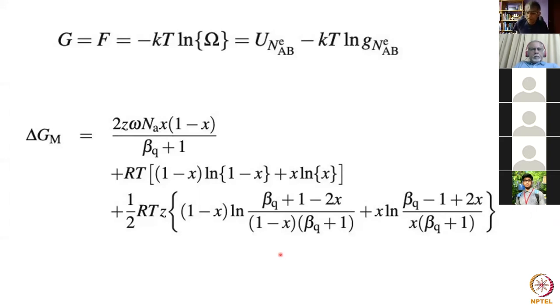The other point is that a lot of the equilibrium thermodynamic data will be derived at high temperatures, because you cannot really achieve equilibrium if you go to sufficiently low temperatures. That means that if you try to extrapolate those functions, you might get some strange results using thermodynamic databases alone. So this method also enables you to extrapolate to low temperatures. And by low temperatures, in the case of nickel and iron, you're talking about temperatures below about 600 degrees centigrade or lower. So in doing our calculations on the transformation start temperatures for the non-equilibrium transformations, like martensite and bainite and so forth, we use quasi-chemical theory to do the extrapolations, okay? Because this is a rigorously founded theory.